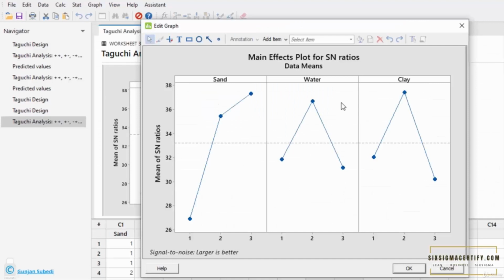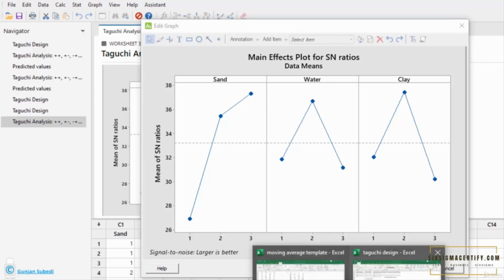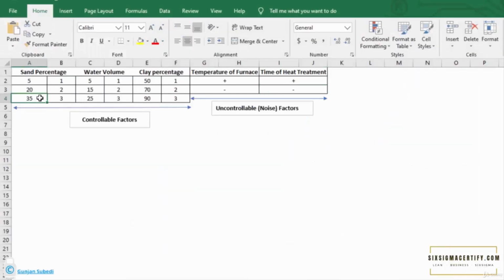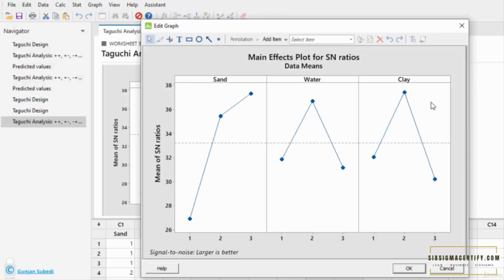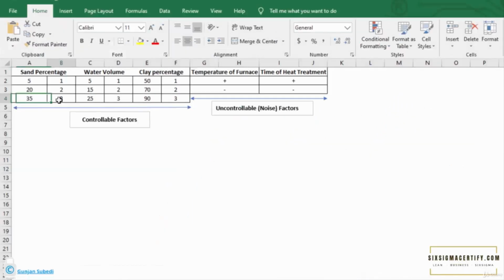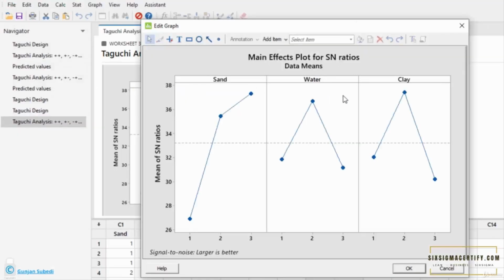Here in the main effects plot for signal to noise ratio, you see that for getting bricks of maximum compressive strength, we have to take sand at level 3. Level 3 of sand means 35 parts sand, level 2 of water is 15 parts water, and level 2 of clay is 70 parts clay. So from this main effects plot only, we could know how the levels of different factors should be selected so as to get the maximum response, which in our case is the compressive strength.